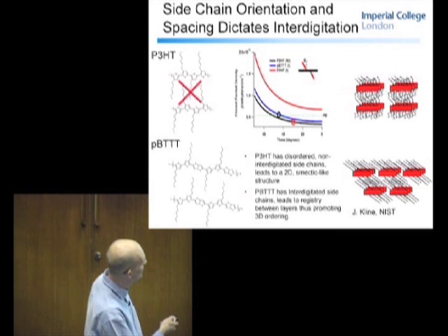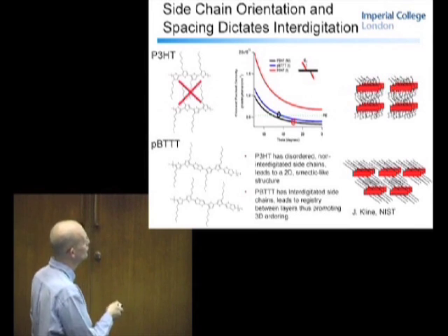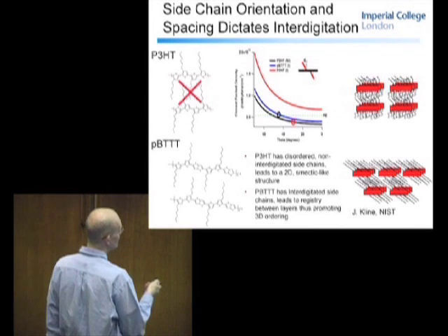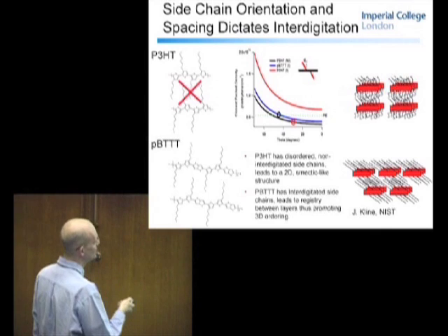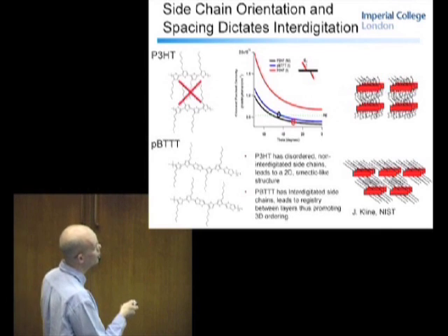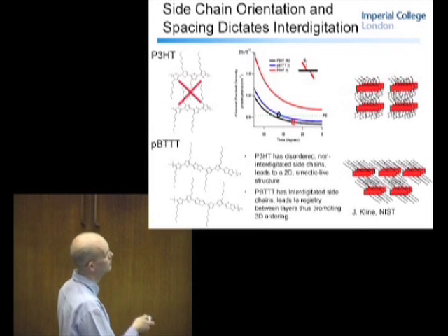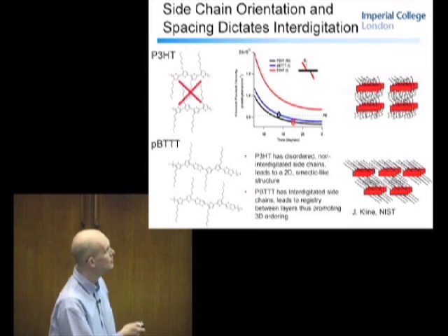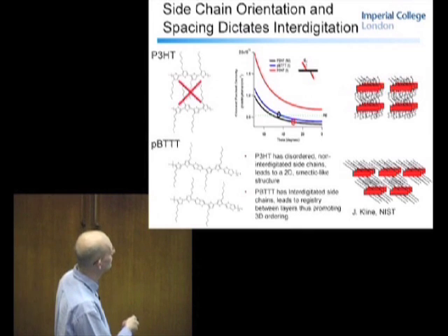You see here that at an angle of about 45 degrees, you approach the side chain packing density of linear polyethylene. And actually, when you do polarized IR measurements and other measurements, you can predict this side chain angle, and it does fall almost exactly at that number. So the types of densities we do achieve with this material are really as high as we can get. This work actually came out very recently in Macromolecules, so it's no longer a manuscript in preparation. It's out now.